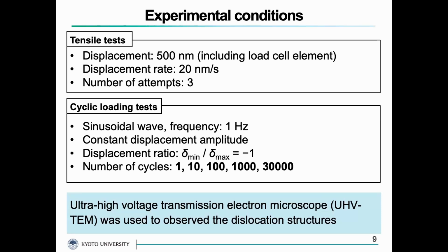Five specimens were subjected to cyclic loading tests, but each specimen was subjected to a different number of cycles. After the cyclic loading tests, these specimens were sectioned, and we observed the dislocation structures using an ultra high voltage transmission electron microscope.